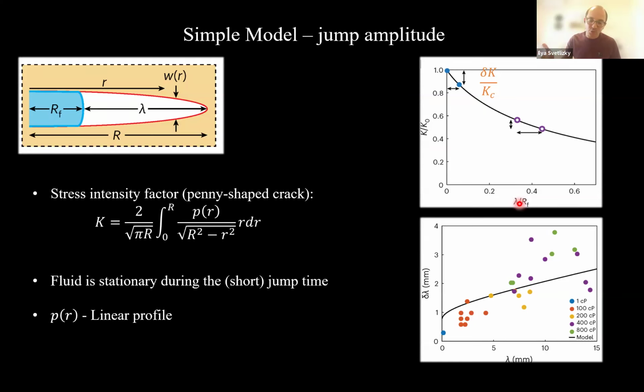These solutions that I told you about that we were not able to utilize do show that there is a continuous transition between something that looks very linear to something that looks very constant just before the crack tip. So this is the pure assumption, and this is the best I can do. Importantly, if instead of a linear profile you take a constant profile, it doesn't make any difference. Or it does, but you will not be able to see a big difference, okay?